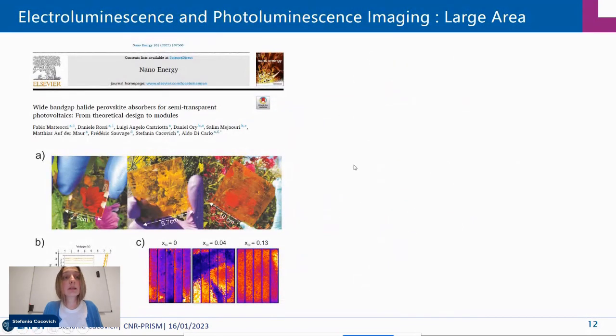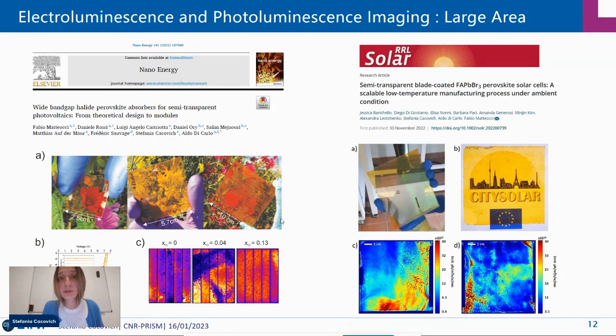But on top of that, we also have a large area imaging system. Here I show you a couple of papers that came out this year. Some of them were also in collaboration with the CNR. And here you can see that we also image at large scale, so not only on a small area, on the micrometer scale, but also when we go to modules, to study, for instance, the homogeneity of the deposition process, also for upscaled devices.